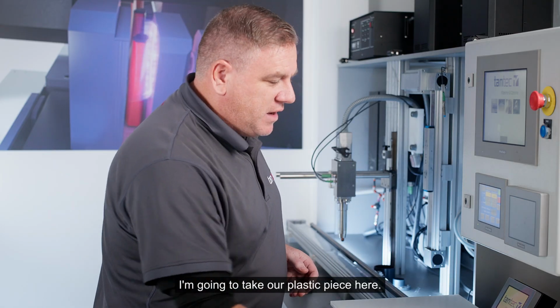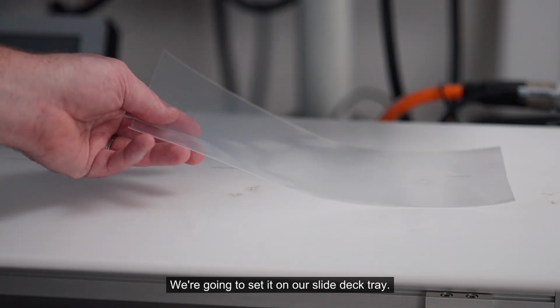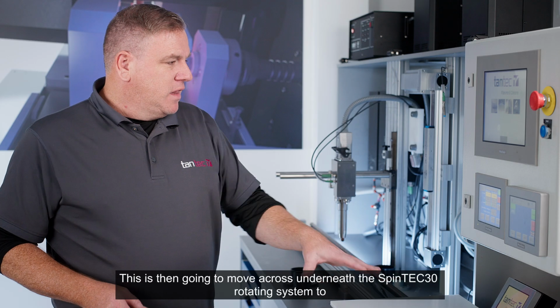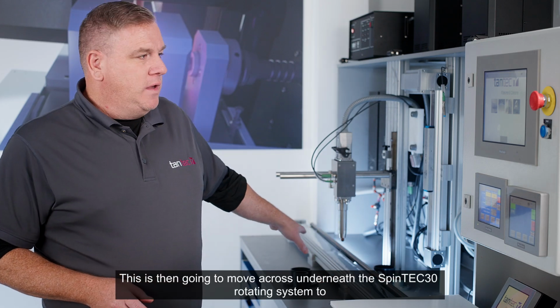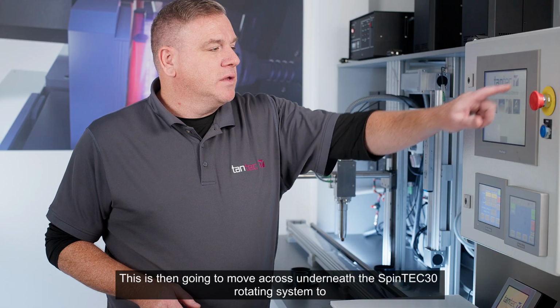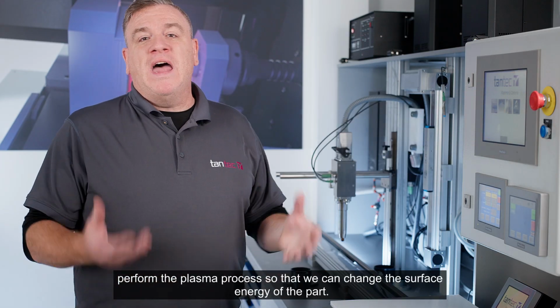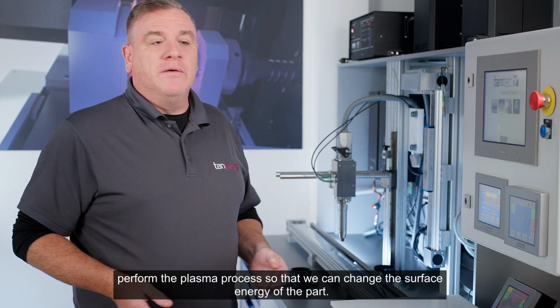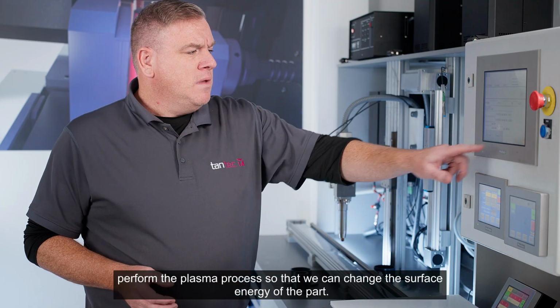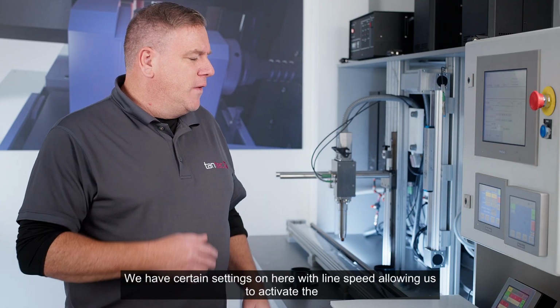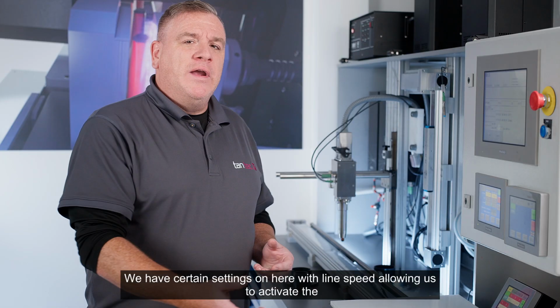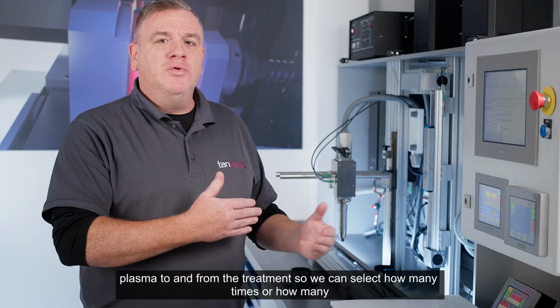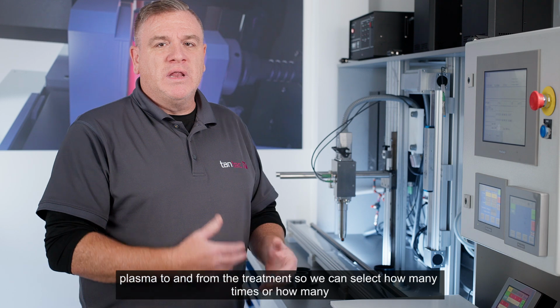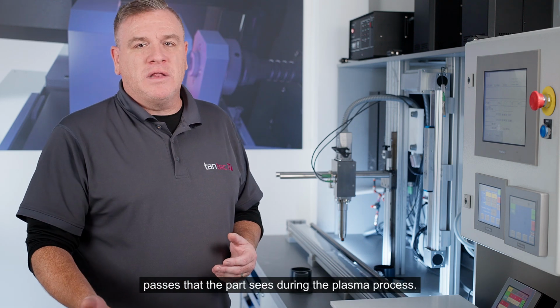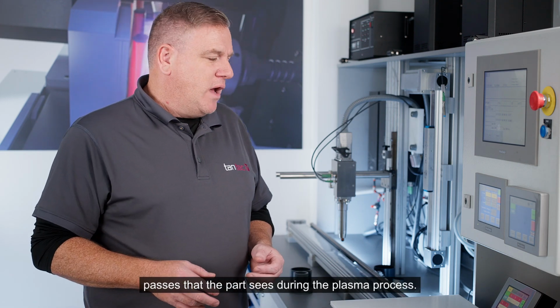So I'm going to take our plastic piece here. We're going to set it on our slide deck tray. This is then going to move across underneath the SpinTEC30 rotating system to perform the plasma process so that we can change the surface energy of the part. We have certain settings on here with line speed, allowing us to activate the plasma to and from the treatment, so we can select how many times or how many passes that the part sees during the plasma process.